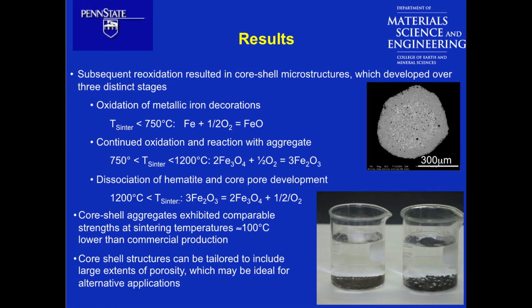And just to give you an idea that this should be something that gets your attention. That bead floats. Okay? It has effective specific gravity of less than 1. And it's because it's a malted milk ball. Dense outer layer, porous inner core. Still high strength. A couple of 100 megapascals.